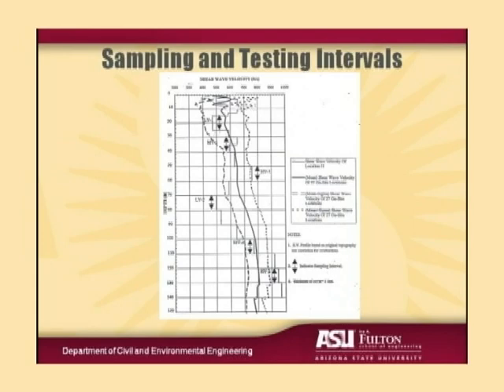So if you look at this figure, we took 6 bulk samples. We had 6 sampling intervals in each of the boreholes. So we took 18 sets of bulk samples. At each location, we did an in situ unit weight test to capture the unit weight of the waste. And then these were the samples we used for our laboratory testing program. So the intervals marked LV were the low velocity samples, MV were the median velocity intervals where we sampled, and HV were the high velocity intervals. And so we had 2 of each in each of the 3 borings.